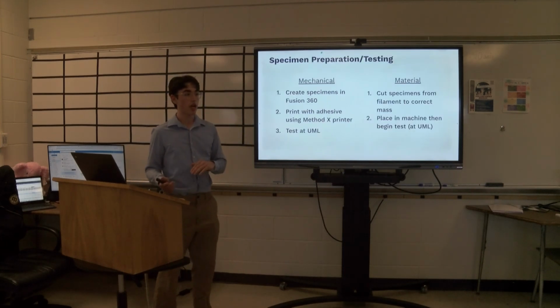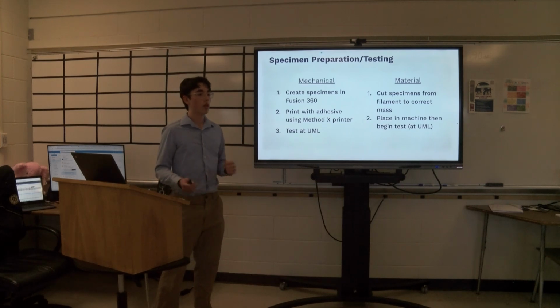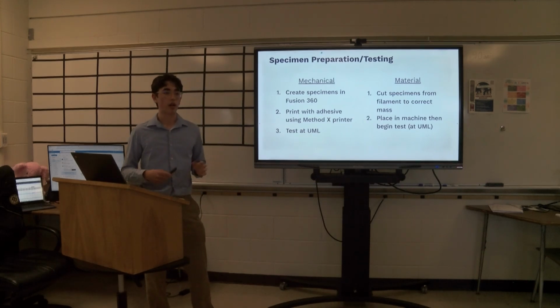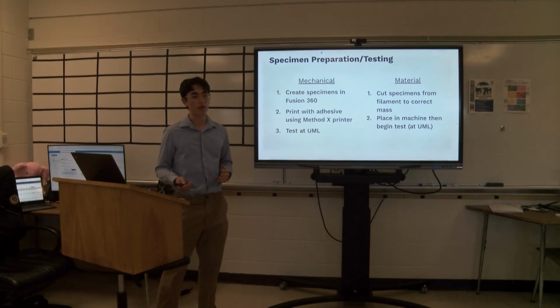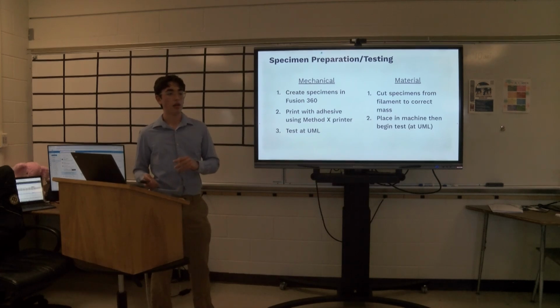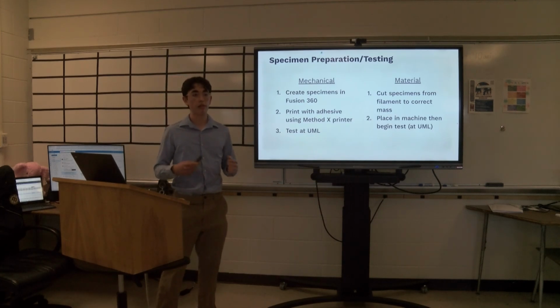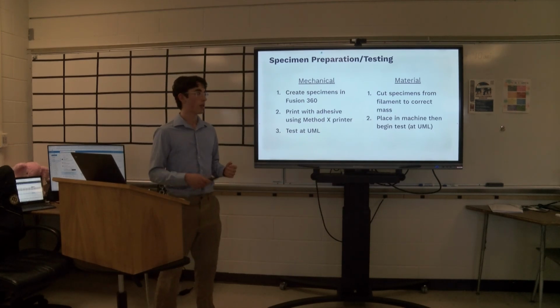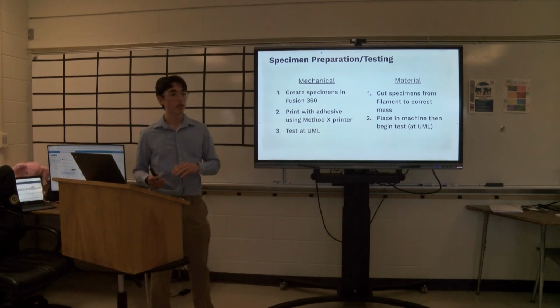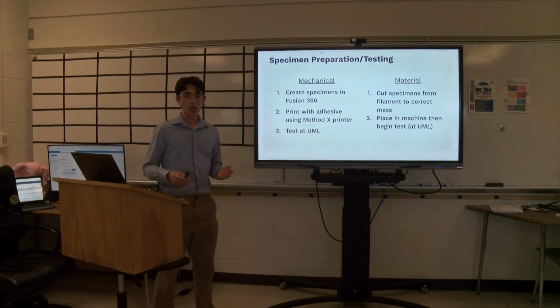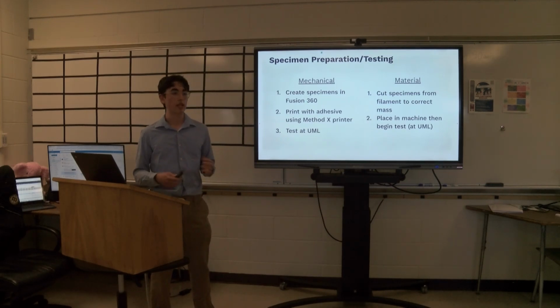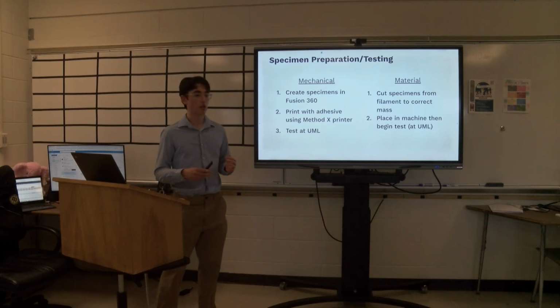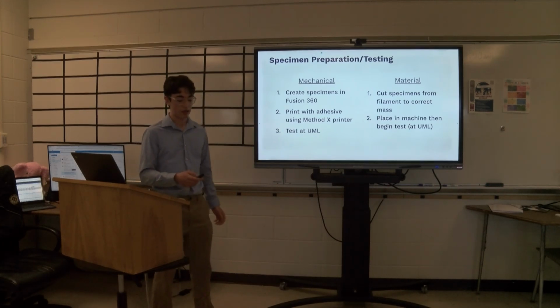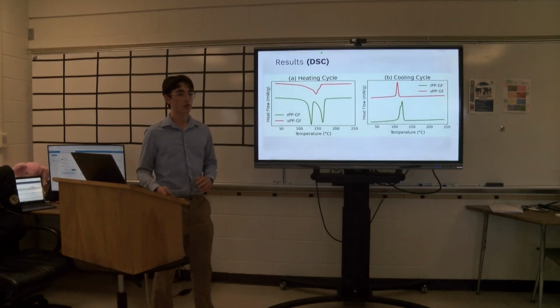Now for these tests, to actually prepare the specimens for the mechanical tests, I first designed the specimens in CAD software, and then I imported these into a 3D printer, printed the specimens, and then tested them at UML. As for the materials test, these specimens were quite small, so they didn't need to be printed. They were just cut directly from the filament and then inserted into the machine, and then testing subsequently began. Now let's get into some results.